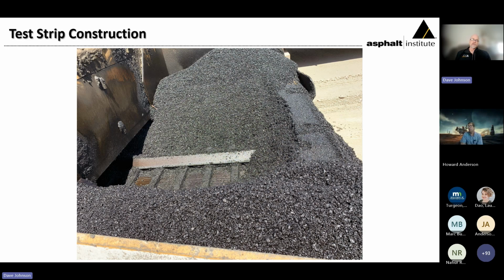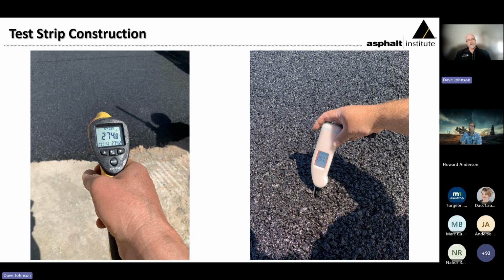The volume of material that's running through a paver is pretty exceptional, and the contractor did have to make some adjustments to their process to make sure that they adequately fed the paver. Of the various things that they looked at in this test strip, this is one of the more valuable pieces of information. Temperature is 275 at the surface and just about 300 internally, so not exceptionally warm.